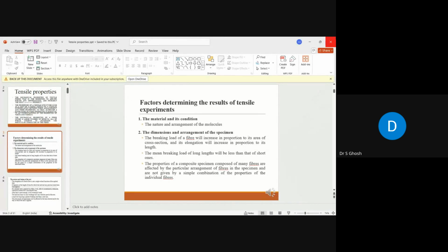So that's why we always say that before testing, go for 24-hour conditioning at an RH of about 65% and a temperature of around 22 degrees centigrade. If the condition changes, you'll find that your data will change. So the condition also affects the results of your tensile experiment. So material and condition affect your results. Sometimes you'll find the same material giving different results, and that's the reason.